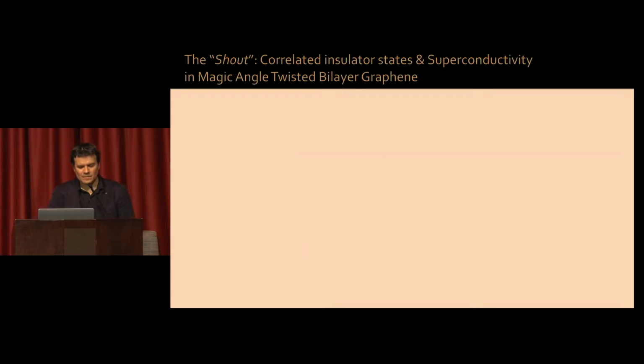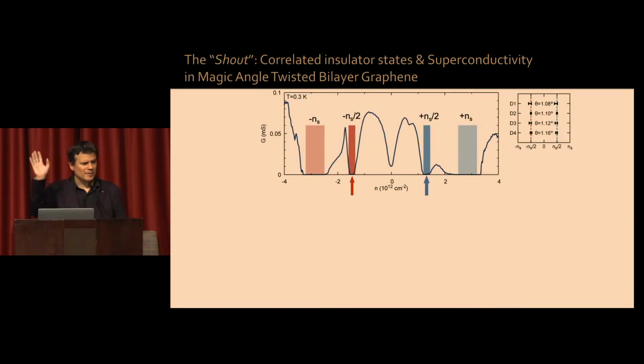So then, what we discovered when we measured these devices was, and this is going to be a bit technical, but I just want you to get away with a message: graphene, which is the best conductor in the world, you put it on top of graphene, which is the best conductor in the world, and when you put it together, it becomes an insulator. And not a regular insulator like diamond, but a correlated insulator. An insulator where it is the interactions between the electrons that prevent them from moving, okay? That was surprise number one.